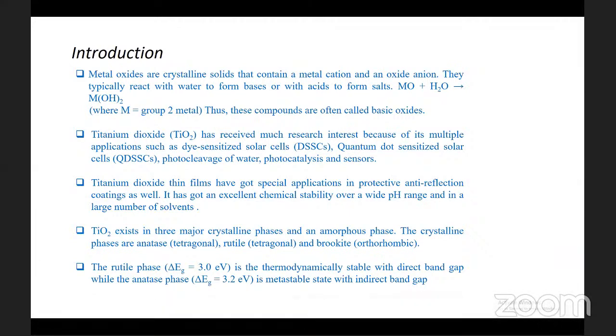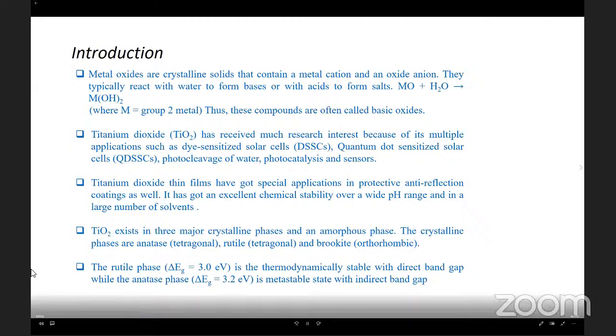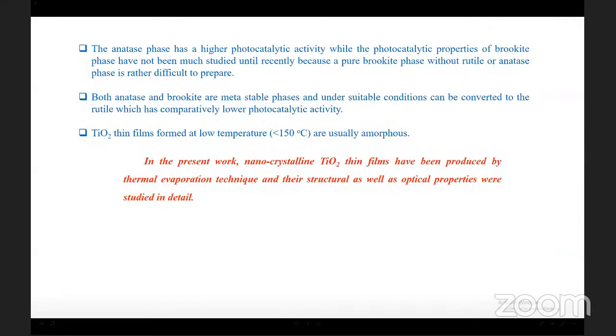TiO2 exists in three major crystalline phases and an amorphous phase: anatase phase, rutile, and brookite. The rutile phase is thermodynamically stable with direct band gap, while the anatase phase is metastable with indirect band gap. The anatase phase has higher photocatalytic activity, while the photocatalytic properties of the brookite phase have not been much studied until recently because pure brookite phase without rutile or anatase phase is rather difficult to prepare. Both anatase and brookite are metastable phases and under suitable conditions can be converted to rutile, which has comparatively lower photocatalytic activity. TiO2 thin films formed at low temperatures are usually amorphous.